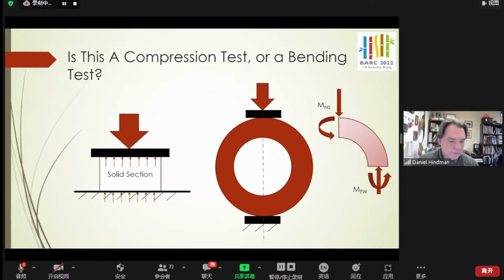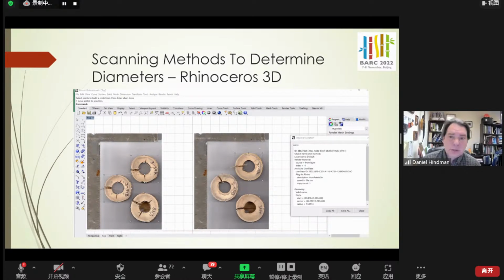Now, an essential part of doing ISO 22157 is to track the diameter and the radius of the rings. And we decided, rather than trying to measure with calipers and have difficulty with that, we would use some computer scanning. So we used Rhinoceros 3D. We scanned the ring sections on a flatbed scanner and then imported those pictures into Rhinoceros 3D. And using several of the tools in Rhinoceros, we are able to pick points along the inner and outer circumference of each of the rings, and determine the radius and diameter from those.